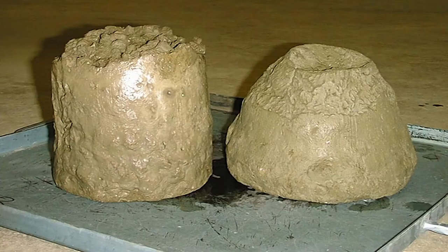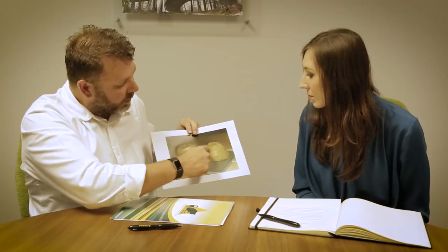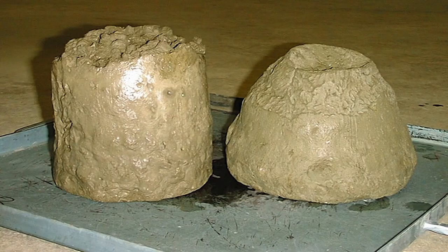It's also important to remember that you need to assess the workability of the concrete. Now, slump is not an assessment of workability. You need to actually tap the base plate, and the workability you need to visually assess. If I may show an example of two slumps that have exactly the same slump value, but you can clearly see that there's a difference in the workability of these two slumps. With the one that has moved down, there's more cohesiveness on this one, there's less cohesiveness on the right-hand side. These are all the types of assessments that you need to make with concrete whilst doing the slump, not only simply measuring the slump itself.